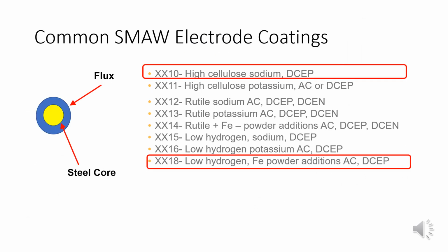Common SMAW electrode coatings. This table lists common SMAW electrode coatings and their properties. Let's focus on 2 highlighted coatings. XX10, high cellulose sodium, offers deep penetration with DC polarity, ideal for pipe welding and positions requiring high adaptability. XX18, low hydrogen with iron powder additions, provides excellent toughness, crack resistance, and ductility with AC or DC polarity. It's commonly used for structural steel and critical applications. Choosing the right coating ensures optimal performance and weld quality.